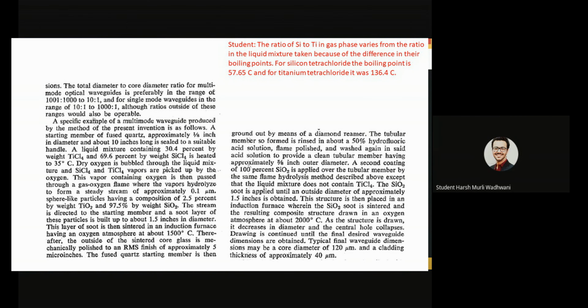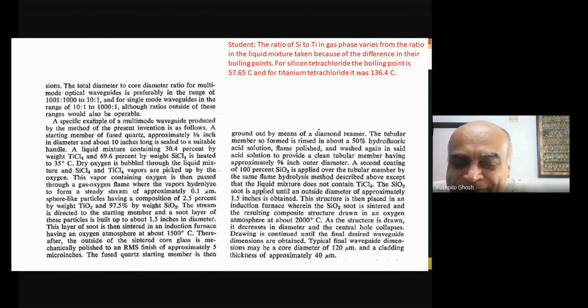We could do the production process the other way. Here, we are increasing the refractive index of the core by doping it with titanium. But if we take the core as pure glass and we lower the refractive index of the cladding using fluorine, I think that can be done, you know, that's why I showed you that plot. Yes. It's very interesting that, of course, why would you want to do that? You see, because remember, fluorine is not so easy to handle. Fluorine compared to TiCl4 would be more difficult to handle. But in principle, what you're saying is correct. What I think one will have to look at is the relative stabilities of these glasses.